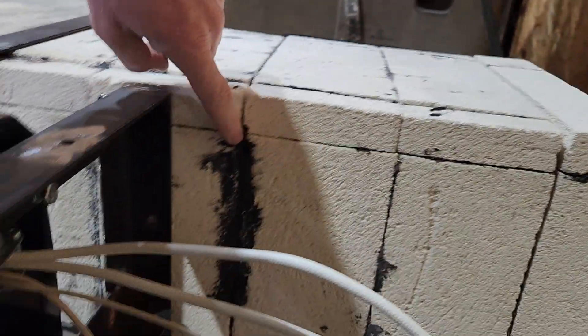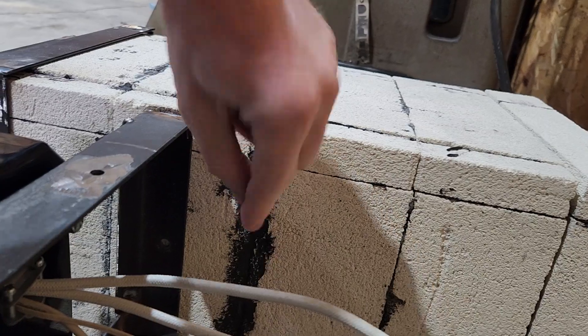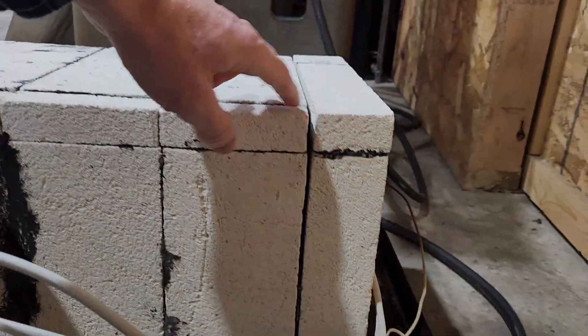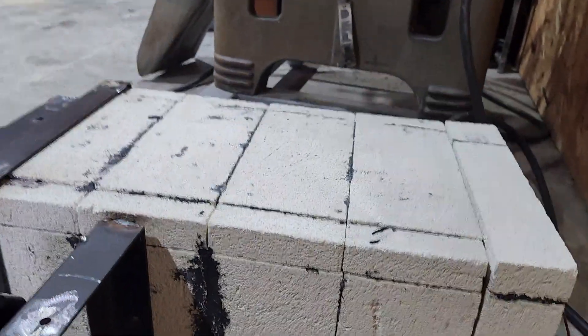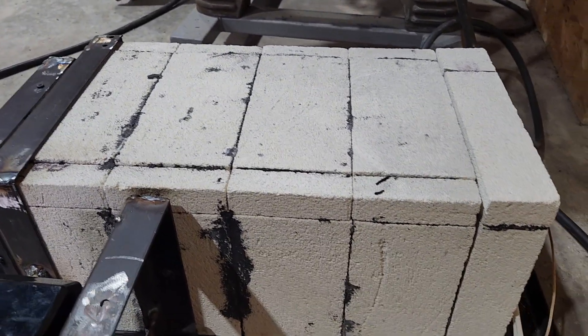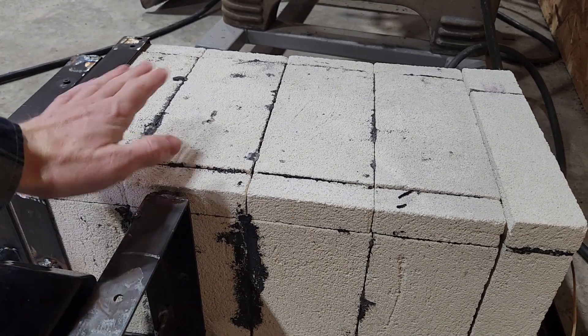When I fired it up it held pretty good. I did get a crack that opened up here when it was at temperature, and when it cooled back down that crack closed back up. On my back panel this also opened up. The mortar that was suggested by RedBeard Ops performed well, but it's not perfect.